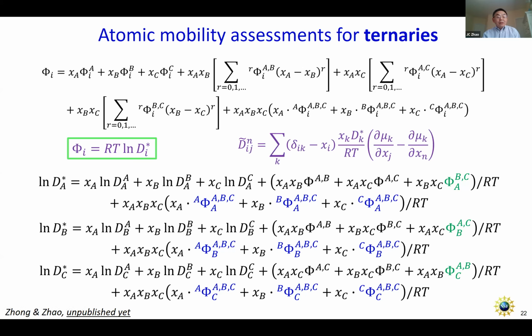Okay, and this is the self-diffusion coefficient of A. This is A impurity diffusion in B, and then A in C. This is the linear addition, and then this is the binary parameter we talked about for the AB system, for the AC system. And then for the BC system, because we are talking about A diffusion in BC, this is the cross binary term. Okay, this is not in the binary system.